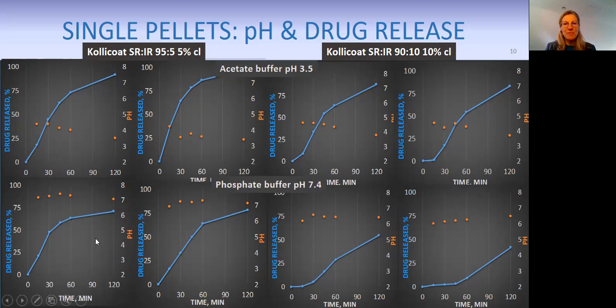So if you have a look at the phosphate buffer, when we expose the 95:5 pellets to phosphate buffer, you can see drug release is not complete. We still have remaining drug in the core, which also explains why the pH within this very same pellet does not go to 7.4, since verapamil HCl and verapamil free base form a mini buffer in the pellet core, so we can't reach the pH of the dissolution medium yet.